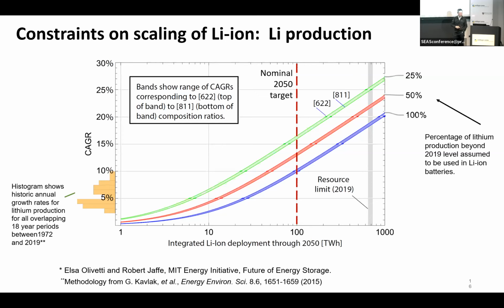So what this chart shows you is that it's not actually that we don't have enough lithium. It's just that the production has to scale at a pace that's very demanding. Now, you can be bullish or not about the rate of increase of lithium mining and production, but this at least illustrates how much it has to be. Each of these curves is 100%, 50%, 25%, how much of the new lithium goes towards the battery. And then the width is just different battery chemistries. This is all NMC, 811 and 622. 811 has higher energy density, a little higher voltage, and uses a little bit less lithium. That's what that means.